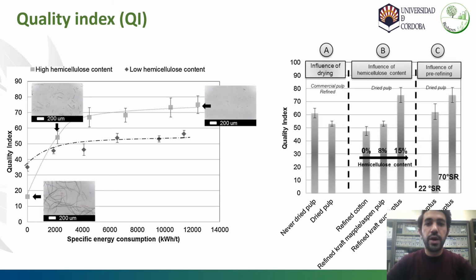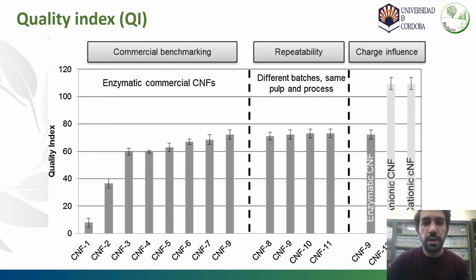In addition, the effect of pre-drying of the pulp and pre-mechanical refining before enzymatic hydrolysis were also studied and analyzed, concluding that these parameters also affect the quality index values. Once the parameters of the quality index were established, different commercial nanocelluloses were studied; those shown in dark color are treated by enzymatic pretreatment and the light ones by TEMPO oxidation or cationization. We observed that there are significant differences even when the different nanocelluloses were obtained by a similar treatment, as we saw in the first part of the graph. In addition, the repeatability of the same process in different periods was also evaluated, obtaining a very similar quality index value between both treatments. We saw the effectiveness of this index for the quality control of the final products.